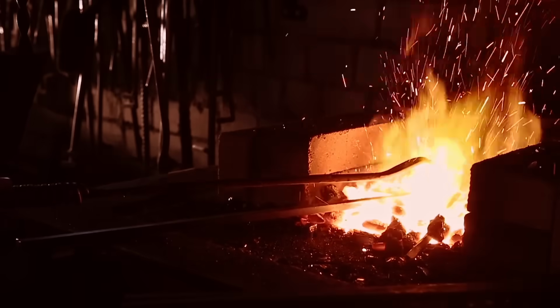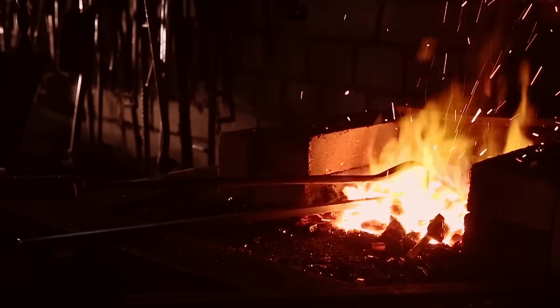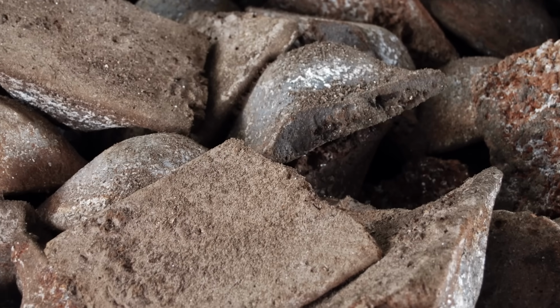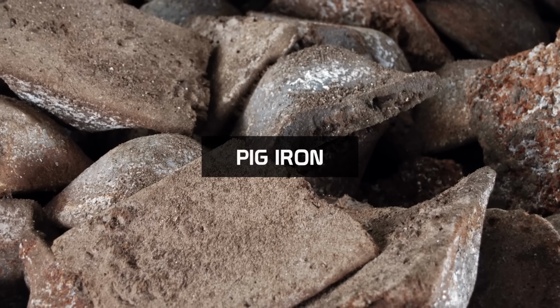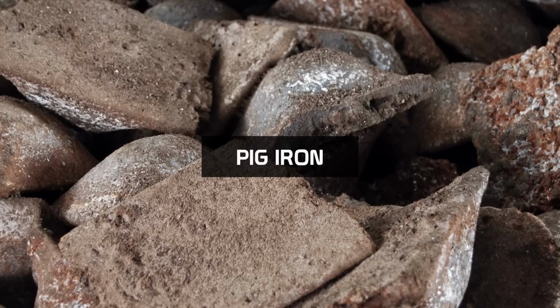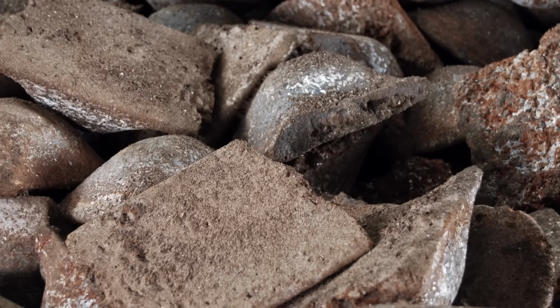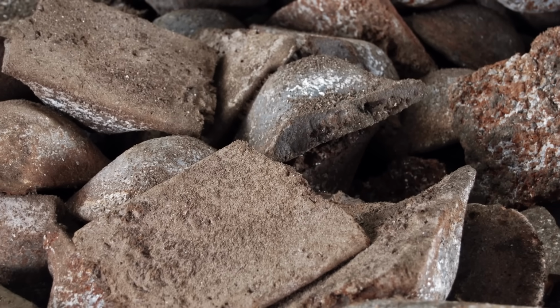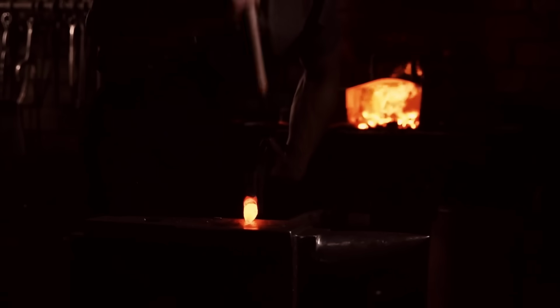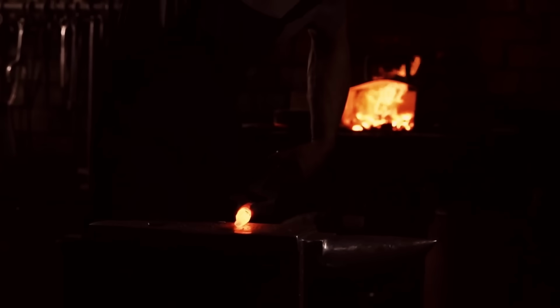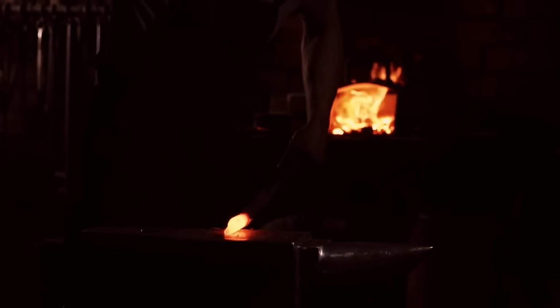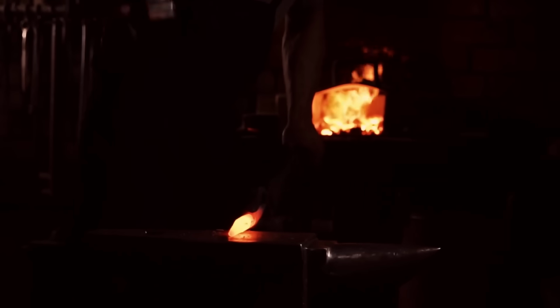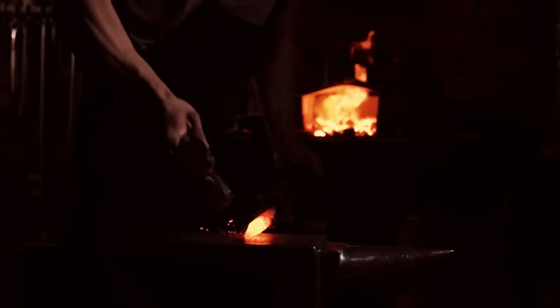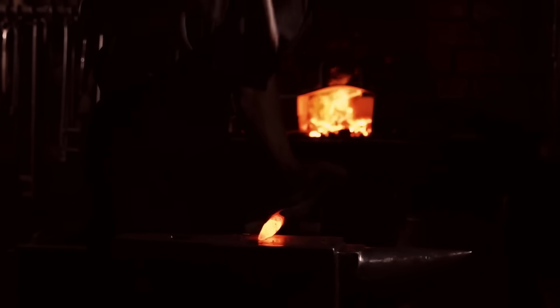At very high temperatures, iron begins to absorb carbon. At around 2.5 to 4.5% carbon content, pig iron is formed. Pig iron suffers from brittleness due to its high carbon content, making it less than ideal for working and shaping. Bloomeries generally mitigated this by not fully melting the iron, but rather hot working it above its recrystallization temperature. The bloom would be forged mechanically to consolidate and shape it, expelling impurities as slag in the process.